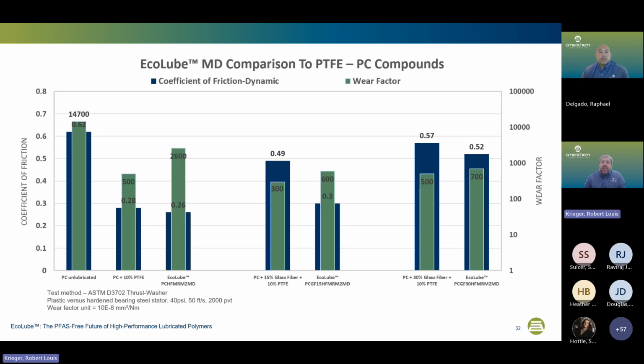Here's similar data in polycarbonate instead of PA66. So again, we have the 0%, 15%, and 30% glass fiber loadings. And again, good parity with the PTFE compounds, 10% versus our EcoLube offering.